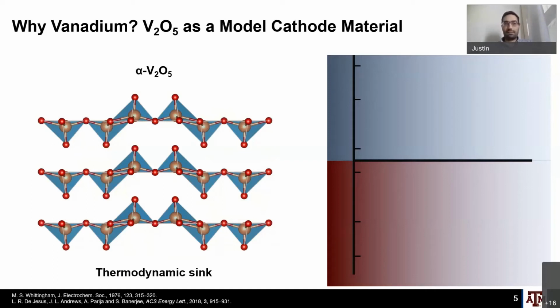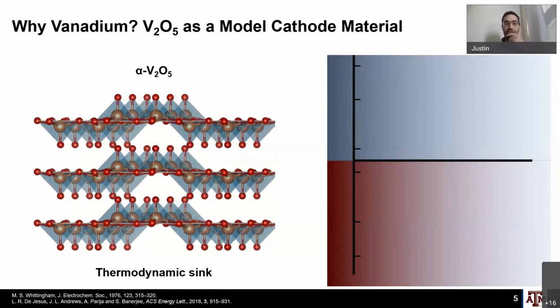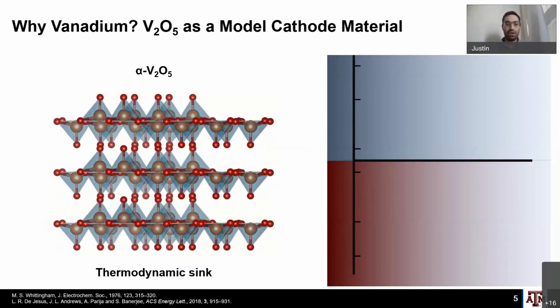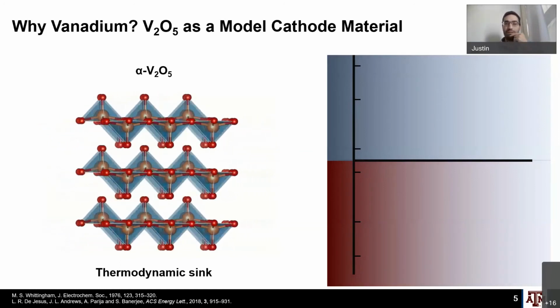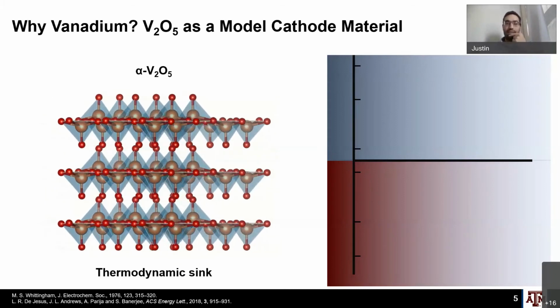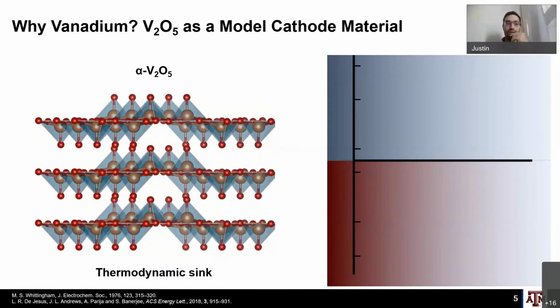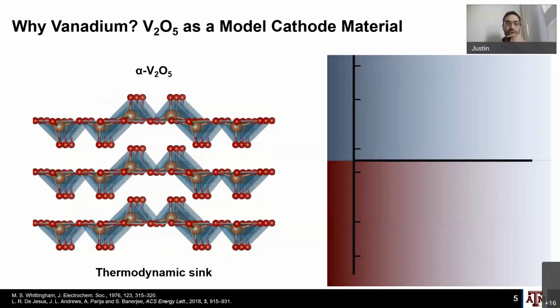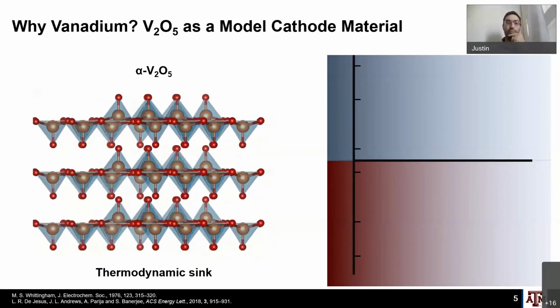And why vanadium oxide is a question that we get asked a lot. Really it's because it's a great model cathode material. It's not the most outstanding material out there on its face. It's the thermodynamic sink of the V2O5 system, and this is the crystal structure. And you can see why, early on in the days of lithium-ion batteries, this was identified as a potentially promising material. It's got a lot of ample room for diffusion of ions. The crystal structure is relatively open.